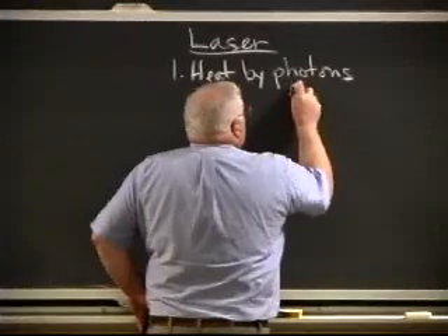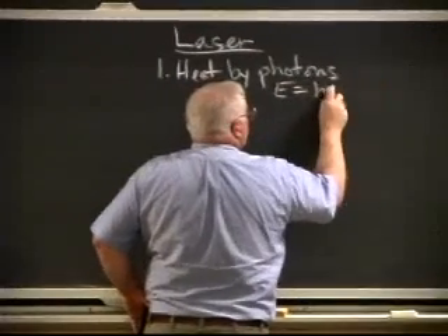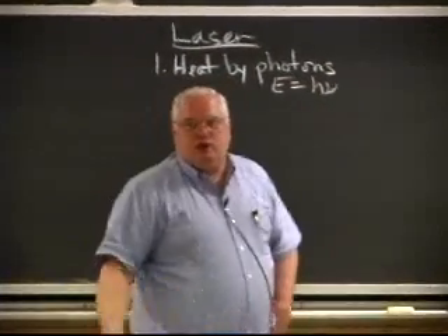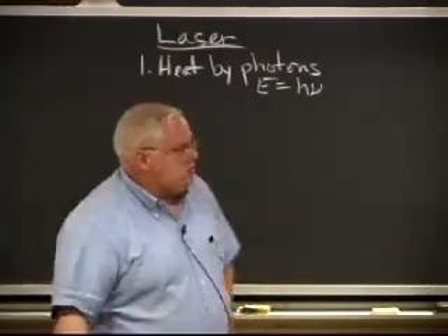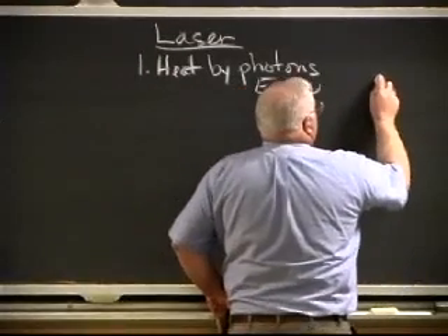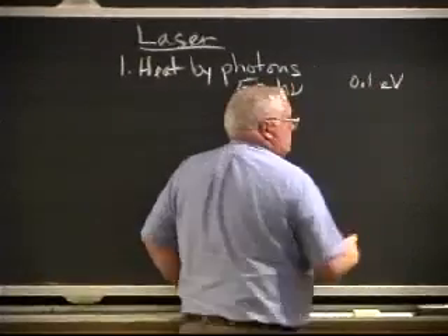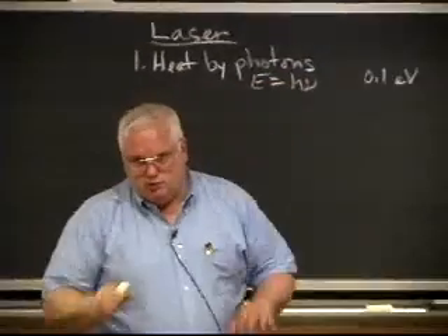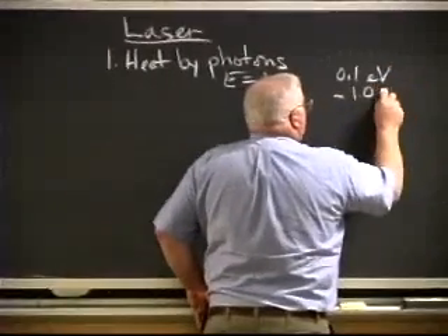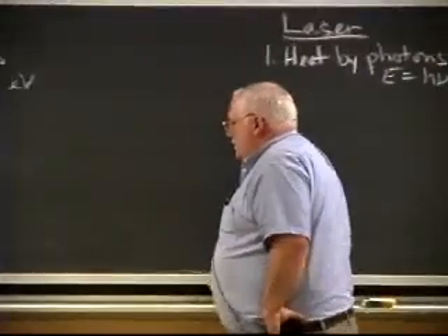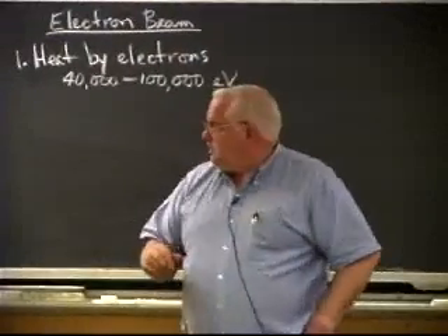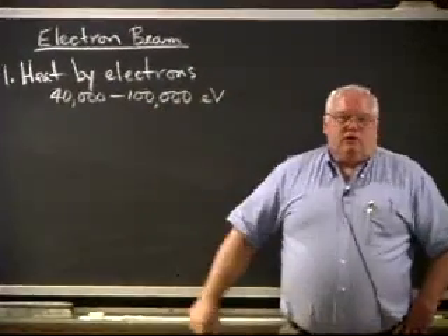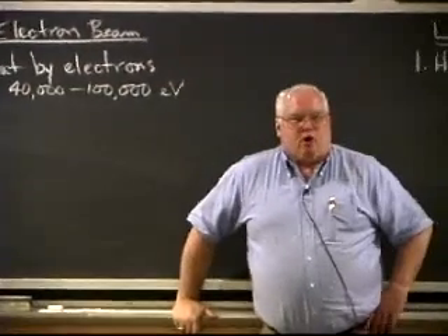Over here, the energy is H nu, and it turns out if I've got a CO2 laser, which is a high power laser at 10.6 microns radiation, the energy is about 1/10 of an electron volt. If I'm using a yttrium aluminum garnet laser, which is a solid state laser, also popular, it's 1.06 micron radiation, and it's about 1 electron volt. So 0.1 to 1 electron volt for the particles that are hitting the surface. So I've got about a factor of 1,000,000 in terms of the energy per particle hitting the surface.